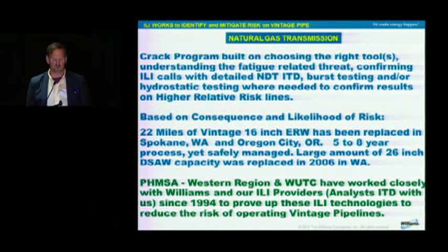A high consequence, high likelihood of failure probably pushes you to replace, like we had to do. We've replaced about 22 miles since we started this Crack Program on vintage 16-inch ERW from the same manufacturer Dave had spoken about, which is Lone Star. Lone Star seems to be problematic for us, but not that it was a bad process. It's just that some of the QA, QC that we've got now wasn't present back in the mid-50s. We don't always have post-weld heat treat on some of our pipe.